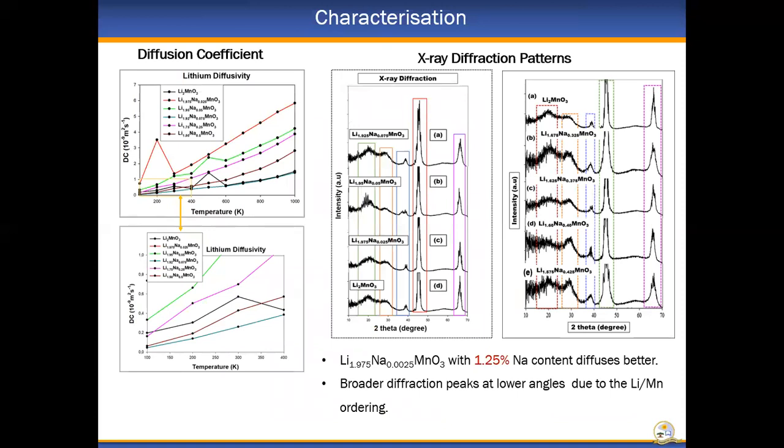Now, the diffusion coefficient plots show that lithium diffusivity is affected by the amount of sodium in the system. As the sodium content was increased, the diffusion coefficient decreased. Now, the X-ray diffraction patterns for the sodium substituted systems are compared with the XRD for the Li2MnO3. We note the broadening of peaks at lower angles as a result of lithium and manganese ordering at the transition metal layers. We also note the shifting of some peaks to lower angles, indicating the presence of sodium,